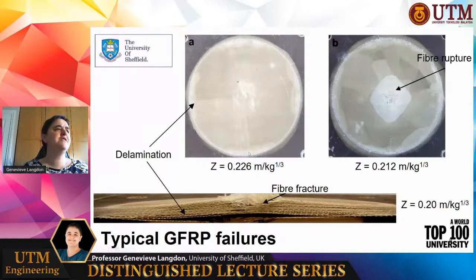And on the left-hand image with the higher Z value, which means that it's got slightly less explosive loaded with it, you can see everything is white. And on the right-hand image where the Z value is slightly lower, which means it's actually been tested at a slightly higher charge mass, you can see this area in the middle has gone even more white. You've got a diamond, and inside that diamond, you've got fiber rupture. So that panel's no longer going to sustain any loading.